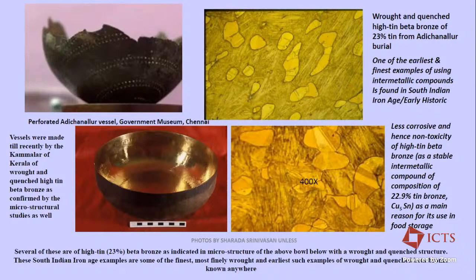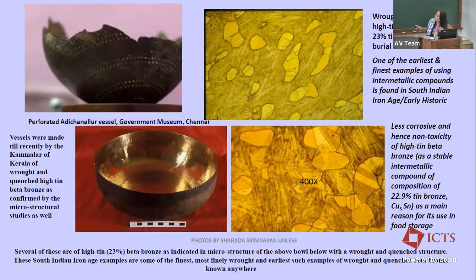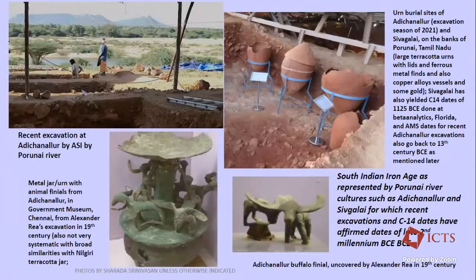And just to confirm that the metallurgy of what was being done in that workshop is exactly the same as what was going on here in the Iron Age. This is a vessel from that same workshop where the inside has been now polished and scraped and so on. And it had the exact same structure of hot-worked quenched beta bronze and the same composition as well of 23% tin bronze. And these are binary bronzes because they don't have any lead added. And that's also an important aspect because they are a class of alloys which seem to be isolating the intermetallic compound phase.